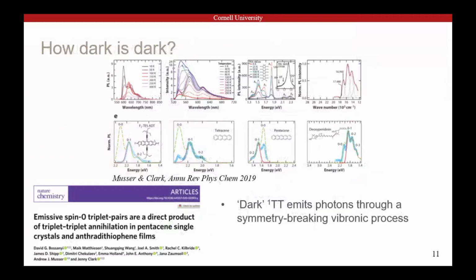And some of this stems from a question I've been asking for about a decade now. How dark is a dark state? It's very easy for us as spectroscopists to say that state is dark, it's not going to absorb, it's not going to emit. But what does that actually mean? And looking in detail in a wide family of singlet fission materials, we found out, well, actually, this dark triplet pair state can be induced to emit photons pretty well, particularly at low temperature.